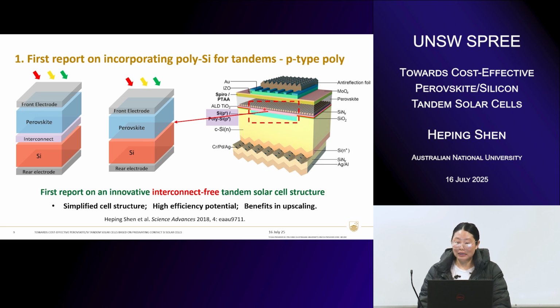Basically, we put the perovskite solar cell on top of the silicon cell directly without the need of any interconnect layer. So it's like what is shown in the middle here. We don't have TCO, we don't have a tunneling junction. So this is the first time that this cell structure was proposed and demonstrated and proven to give high efficiencies. And we named it an interconnect-free tandem cell structure.